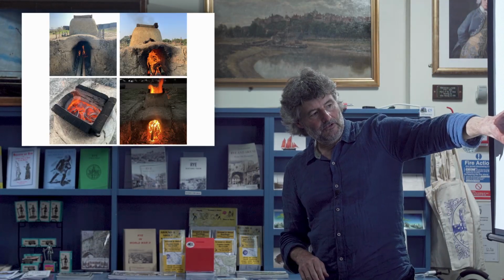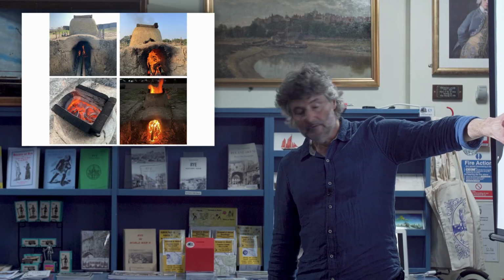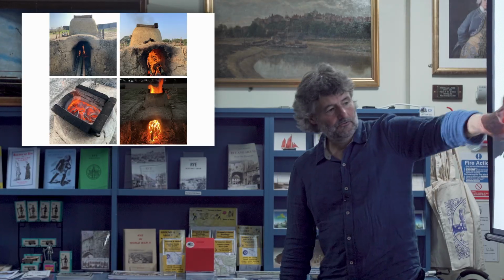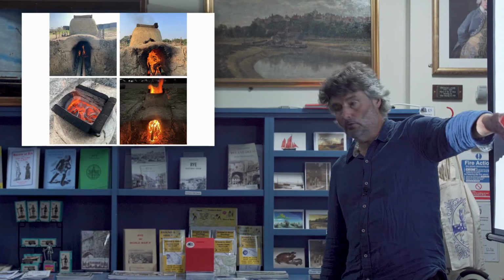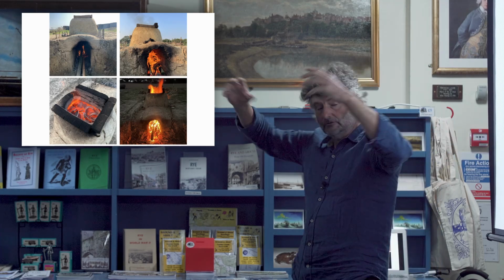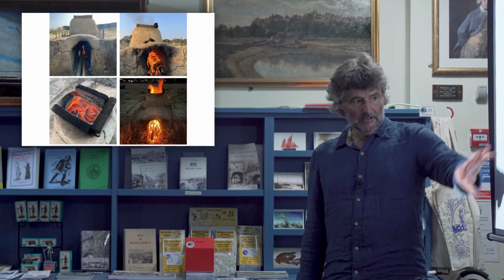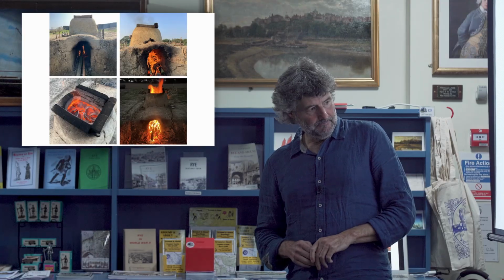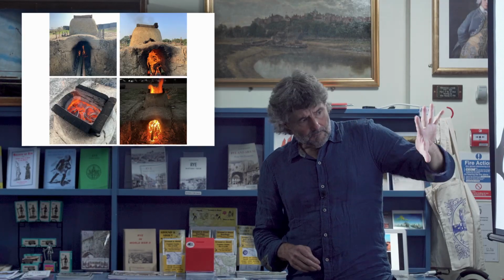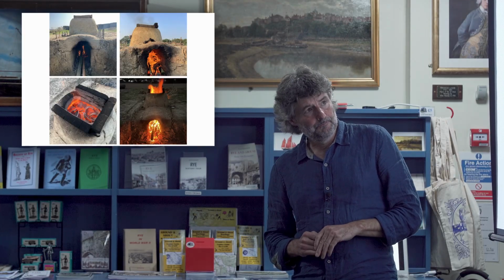But once we're through that phase, you can then start to fuel up the kiln, and by about 500-600 degrees it's starting to glow inside. This is probably 600-700 degrees, and you can see the whole of the inside of the kiln, the structure, the pots and everything are now glowing with a fairly deep red, which is indicative of that temperature.